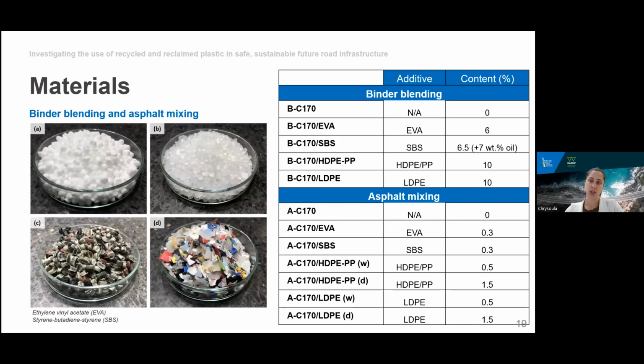So for our investigations, we used a C170 as the base bitumen, and we modified it with some of the commonly used EVA and SBS, and 2 types of recycled plastics. We chose a low-density polyethylene from waste plastic bags, which had been pelletized and was sourced from Western Australia, and a commingled plastic of high-density polyethylene and polypropylene in its as-shredded form, sourced from Queensland.